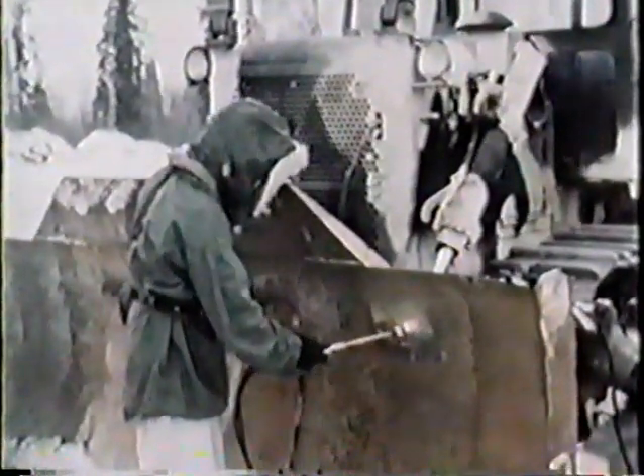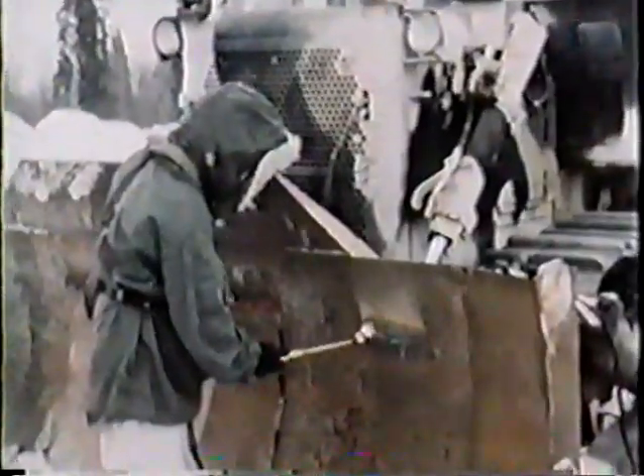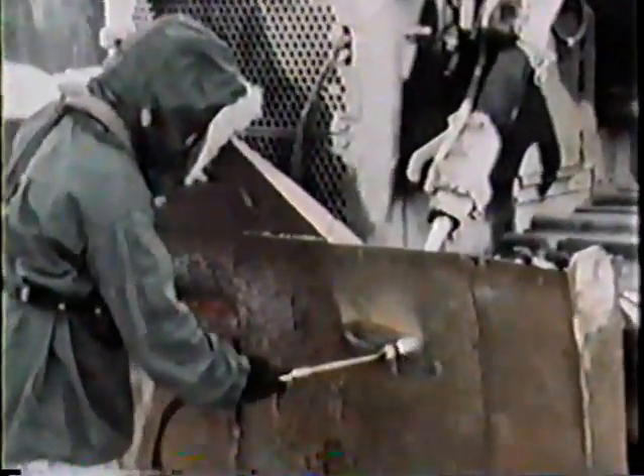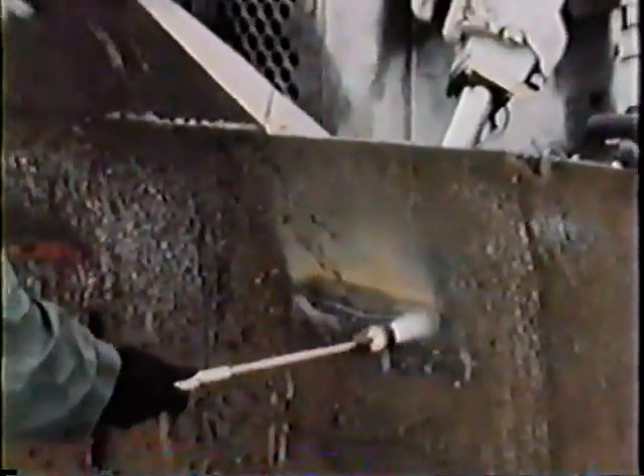In our case, the repair area must be maintained at around 1200 degrees Fahrenheit. For repairs in the field, maintain this temperature for 30 to 60 minutes, a job that will be done by an insulating blanket. Otherwise, cooling may take place too rapidly at extreme cold temperatures. The purpose of stress relieving is to prevent hardness and brittleness in the fusion zone.